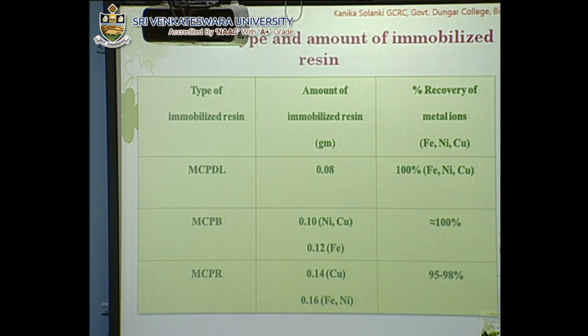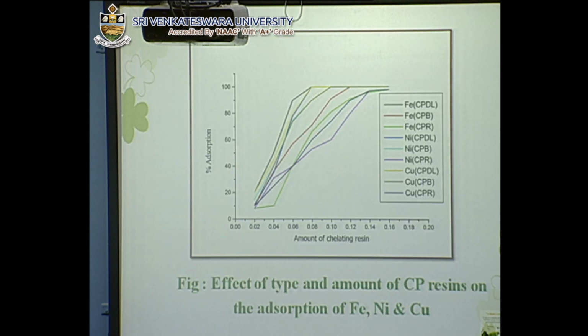As you can see in the table, the Calotropis procera dry latex is better as compared to modified bark and root. In the case of Calotropis procera dry latex, we are able to recover 100% of metal ions using 0.08 gram of the resin. This is the graphical representation of the data.